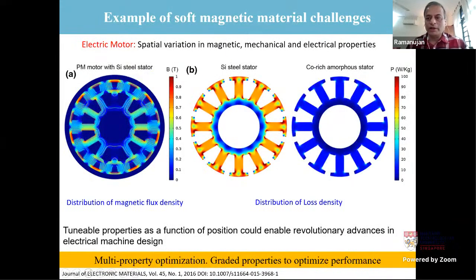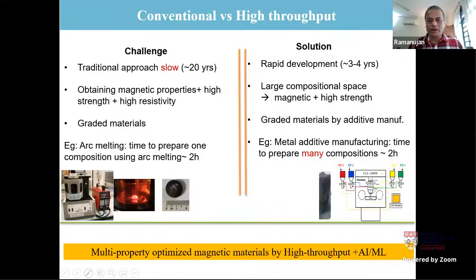So for example, in the case of a soft magnetic material, even the magnetic properties themselves vary with position. So you would actually ideally like a graded composition in order to optimize the spatial properties. So there are many new challenges which are coming up for the next gen magnetic components. But the traditional approach to developing this has been very slow.